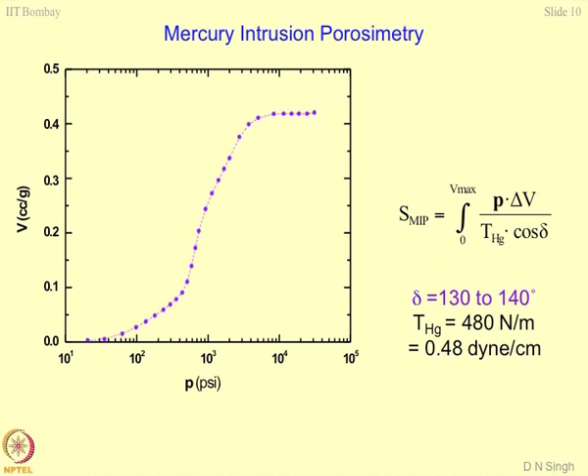The third method is mercury intrusion porosimetry. The volume of mercury intruding into the system is measured as a function of applied pressure. You get a typical S-curve showing that the pores are well distributed and all sorts of pores are present in the system. If you hypothetically got a vertical line, it would mean one pressure fills all the volume — meaning the system is highly porous, but that type of geomaterial is of no use.